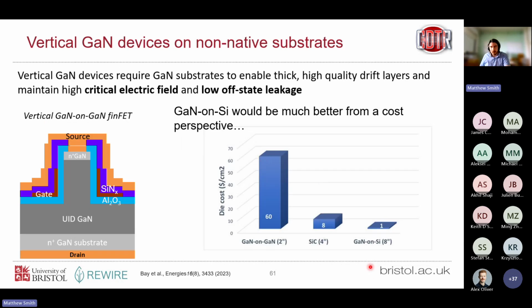Okay, so for the next few minutes, I'm going to talk about our work on GaN on silicon. So I mentioned earlier that for vertical GaN devices, we work on these gallium nitride substrates. So that's necessary, or so the thinking goes, to reduce our dislocation density, because now the current path is vertical in these vertical devices. Current path is in the same direction as our dislocations. So we need to minimize the amount of dislocations by using gallium nitride substrates.